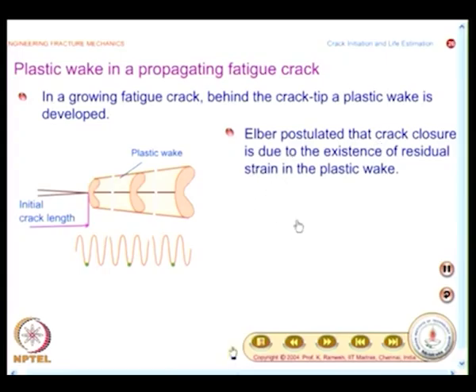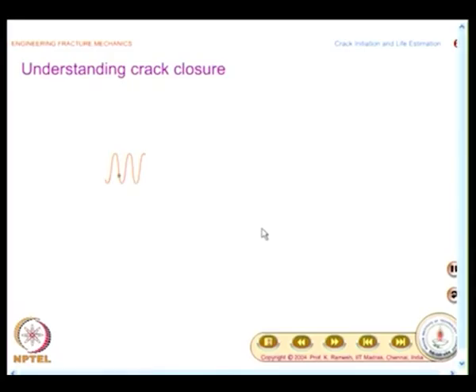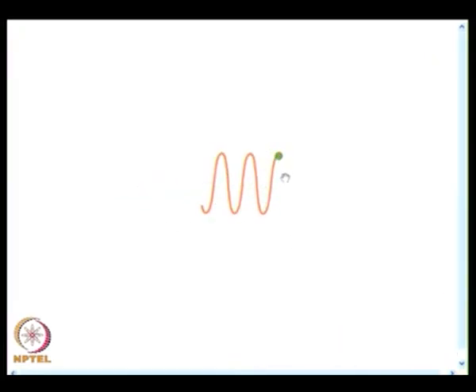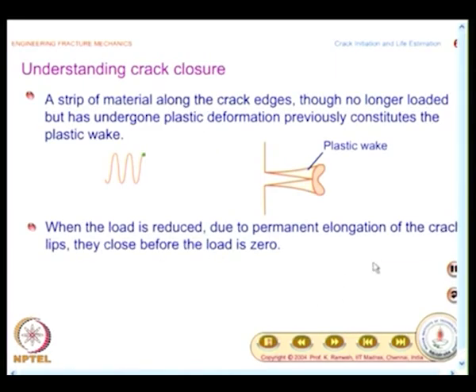We will see how. I have an animation which explains that, but you have to recognize, as the crack grows, the plastic zone size keeps increasing, and also formation of plastic wake, and this goes with your cyclical loading. That is what is depicted below. You would have noticed that there was an oscillation. So, I think what I can do is I can quickly zoom it. So, you will see this only shows that I am looking at a cracked specimen after this kind of loading. Okay. So, what you find here is